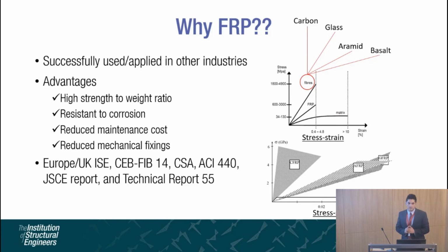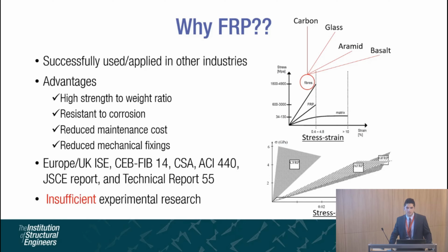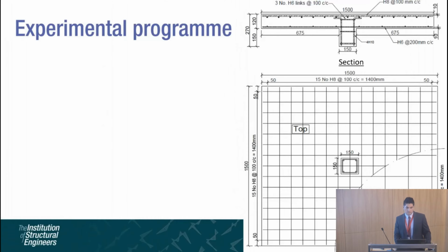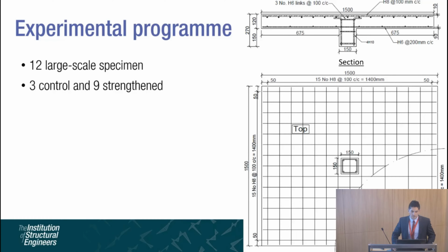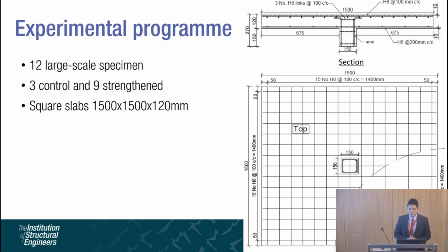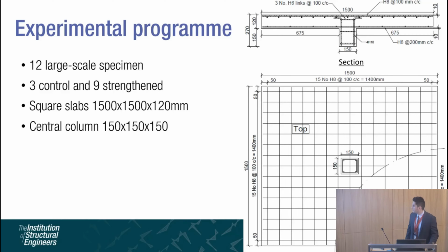Currently, there are design guidelines for strengthening of existing structures, but they do not cover strengthening of flat slab junctions with FRP materials. And there is insufficient experimental data to support the development of codes in this area. In the experimental program that we have conducted, a total of 12 slabs were tested. 9 of them were strengthened with FRP materials. 3 of them acted as control samples. They were square slabs with dimensions of 1.5 by 1.5 meter, with a thickness of 120 millimeter, and a central column of 150 by 150.